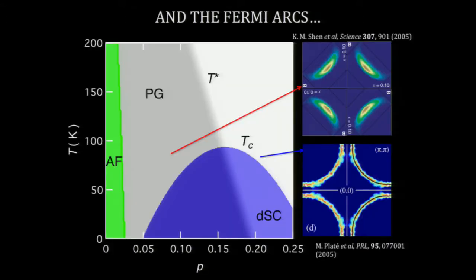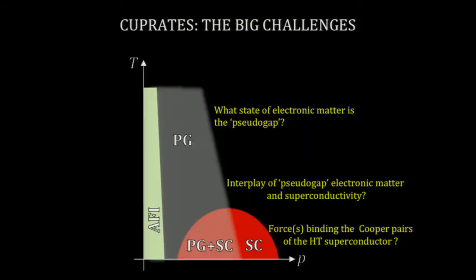And to make it worse, they seem to introduce certain objects that we find quite mysterious. For example, if you look in the pseudogap phase and look at photoemission spectroscopy and try to look for a Fermi surface, you don't find a Fermi surface. You see these open arcs. So there isn't even a closed contour when you're in the pseudogap regime. If you keep doping the system and get to this side, you do find that eventually it does close. But the question is, what is this object here which doesn't have a closed Fermi surface?